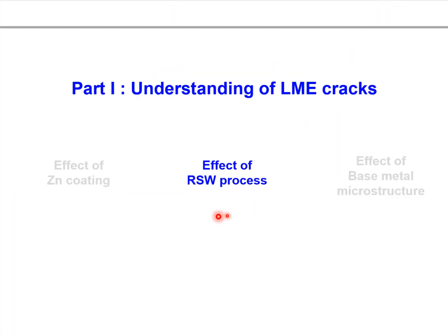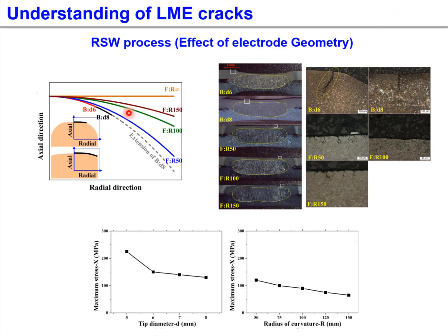Secondly, the effect of resistance spot welding process on LME cracking. As part of the welding process, electrode geometry is well known as a key factor for LME cracks. The results suggest that the radius of the electrode is the most critical design parameter which controls the critical stress for LME cracking. Moreover, a larger tip diameter and higher radius of curvature display a lower maximum stress level, which results in lower LME sensitivity.